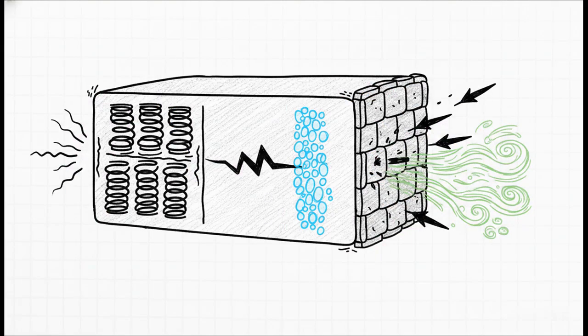Aside from carbon, engineers have designed some other totally ingenious composite armors to solve very specific problems. For instance, MgO spinel composites lower the overall thermal expansion and resist alkali corrosion perfectly. MgO mixed with zirconia adds transformation toughening, which actually absorbs energy to stop cracks from spreading in high-temperature crucibles. And MgO combined with silicon carbide forms protective forsterite layers that block oxygen intrusion. We are essentially customizing the microstructure to fit whatever danger the material is facing.